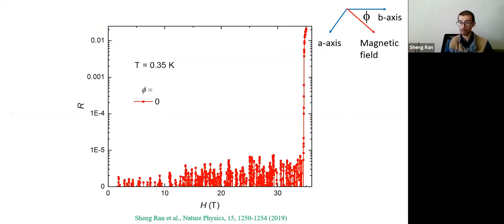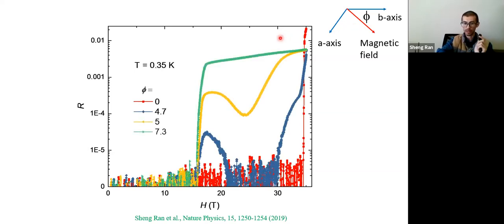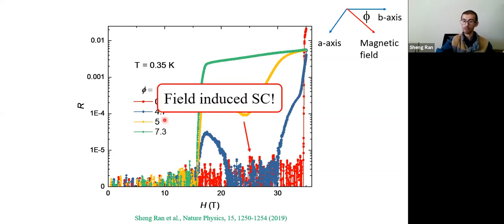Now, we don't have to apply the magnetic field along any special axis. We can rotate it from the b-axis, for example, towards the a-axis. When we do that, you can see at some small angle, the resistance was 0, and then at 15 Tesla it goes to a normal state, and then it comes to 0 again, and eventually this goes to normal state. So this is exactly called field-induced superconductivity.